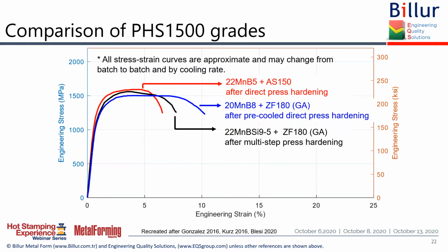And if we compare all these PHS grades, again, all stress strain curves are approximate and they may change. Don't judge them and say 20 MnB8 has a longer elongation. Depending on the cooling rate, these may change significantly. But as you can see, all three would have approximately 1000 megapascal as their yield strength, about 1500 megapascal as their UTS.